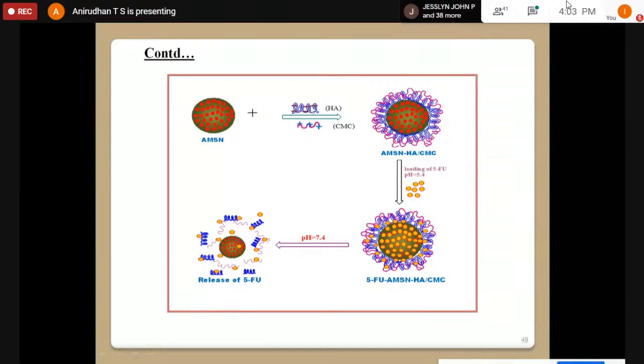So here hyaluronic acid has a negative charge, then carboxymethyl chitosan has a positive charge, the other one is negative. So these two chemicals interact with the mesoporous silica having an amino group. We have a structure like this. So aminated mesoporous silica associated with hyaluronic acid and carboxymethyl chitosan. Then you introduce your drug. Here the drug is 5-fluorouracil. This 5-fluorouracil is introduced in your core structure or even in your layer structures because of this polymer network having two different layers, positive and negative charge layers.